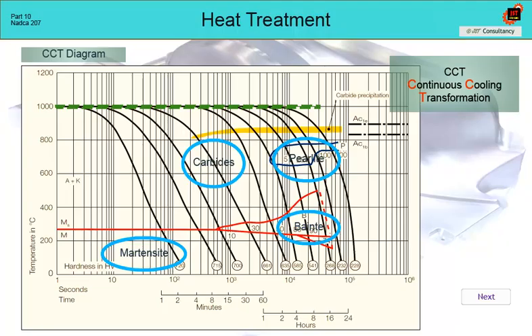In the case of quenching of steels for hot work, according to NADCA 207, two things are important. Cooling should be fast enough to achieve a martensitic structure, see red curve, and fast enough to prevent precipitation of carbides along grain boundaries, see green curve. Only if these two conditions are met can we move the material towards the upper limit of impact toughness values.